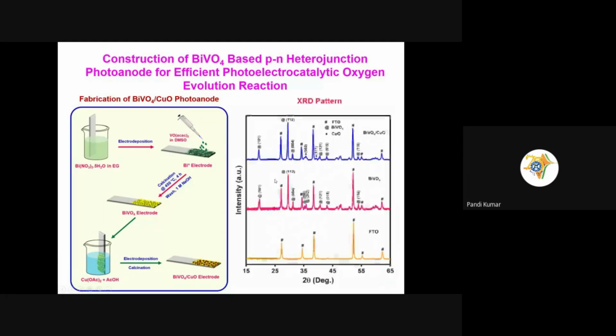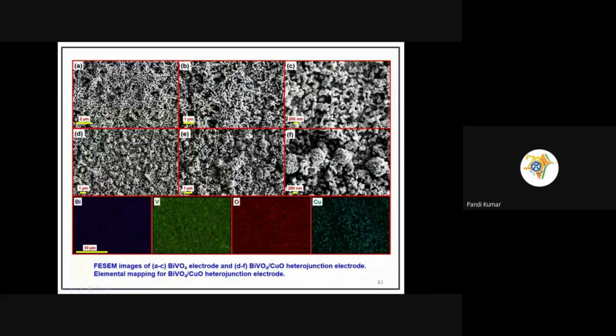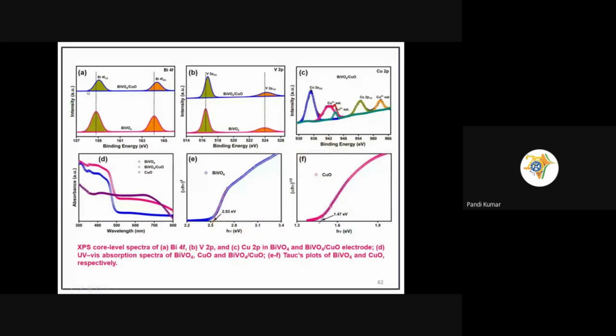So the XRD signature peaks reveal the clear formation of copper oxide over the bismuth vanadate surface. So this is the pristine one. This is after forming the heterojunction. Then the FESEM analysis shows excellent morphology before and after deposition of copper oxide. The elemental mapping also concludes the existence of only four elements in the thin film. Then the XPS analysis, especially, we want to prove the formation of the heterojunction.